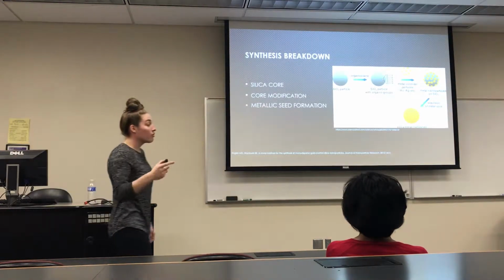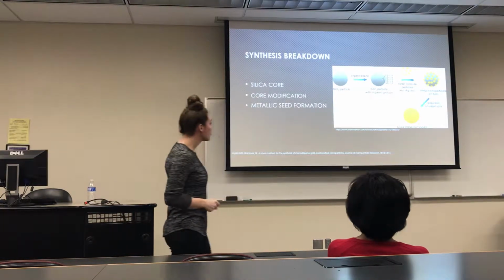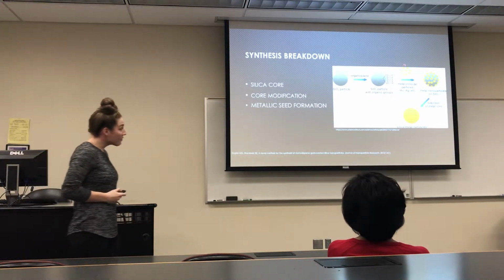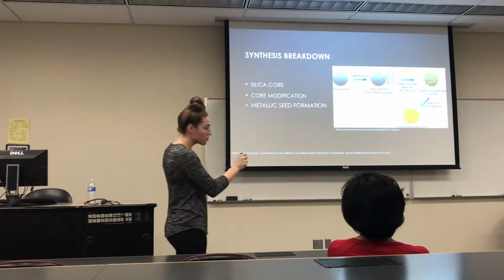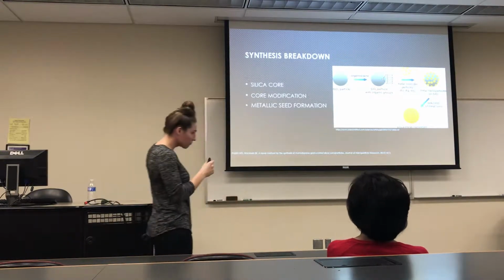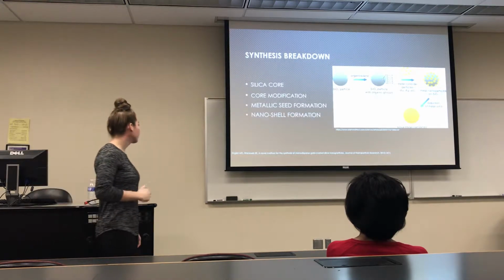So the amine is also going to give a positive charge in solution, which can readily bind and create an even larger affinity for that negatively charged gold particle. And then finally, after we seed it with just a small amount of gold, we can build from there and get reduction of larger layers of gold to build up that entire nanoshell.